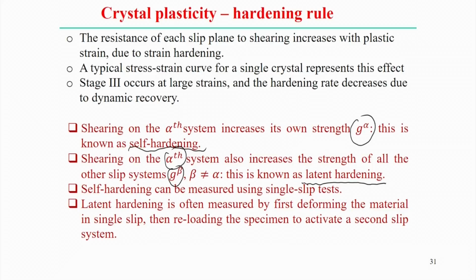Therefore, self hardening can be measured using a single slip test, but latent hardening is often measured by first deforming the material into single slip, then reloading the specimen to activate the other slip systems, or maybe to activate the second slip system. So these are the ways to measure the hardening effect, whether it is self hardening or latent hardening. Basically self hardening is the increment of the strength level for a specific slip system, a direct effect on that, or secondly the increment of the strength level for a specific slip system that will affect the other slip systems, in the deformation behavior of a single crystal structure.